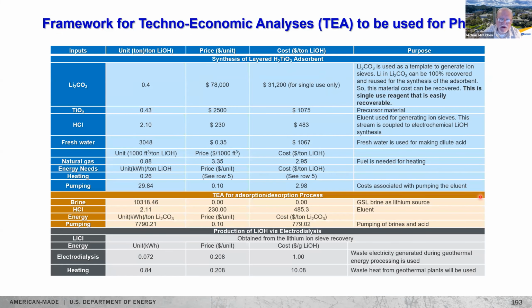Shown here is our techno-economic analysis for absorbent synthesis in blue, adsorption elution in orange, and electrodialysis in gray. Units used, prices, and cost per ton of lithium hydroxide are shown. Note that the lithium carbonate used to make the absorbent template, which is required for any ion sieve method, is fully recovered and reused. So its initial cost is shown, but not included in the analysis. The only use of fresh water is to make the initial dilute hydrochloric acid for elution. This water is recycled along with the hydrochloric acid.